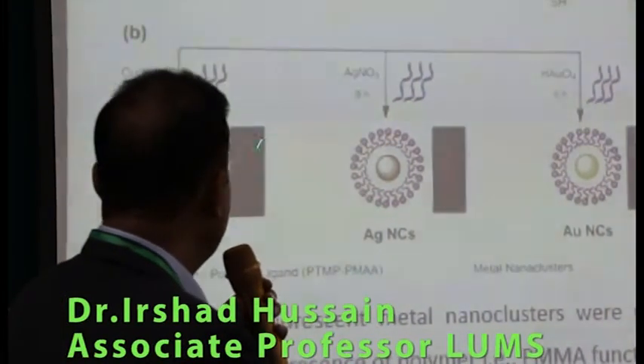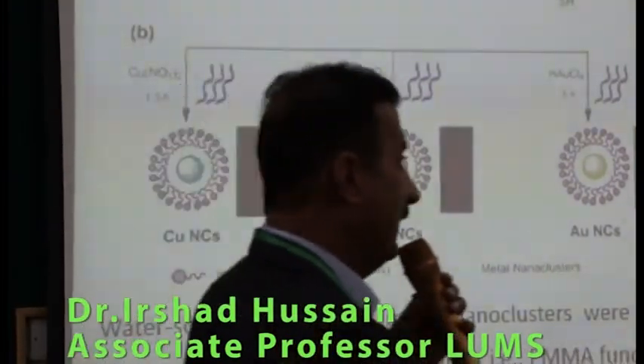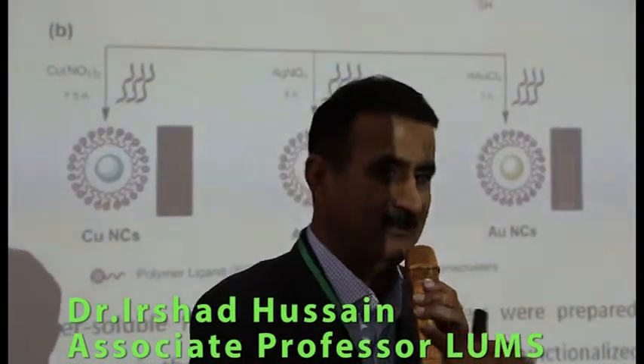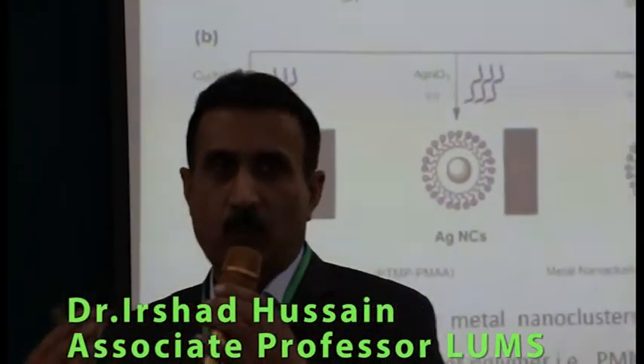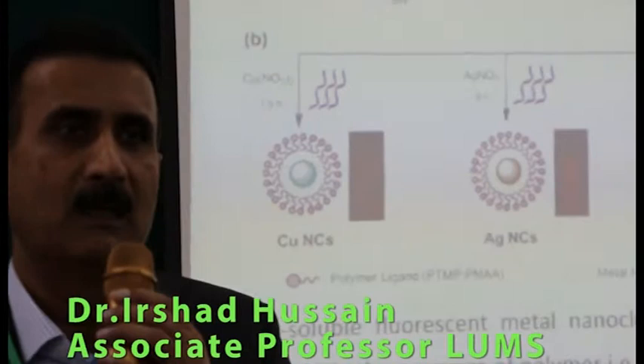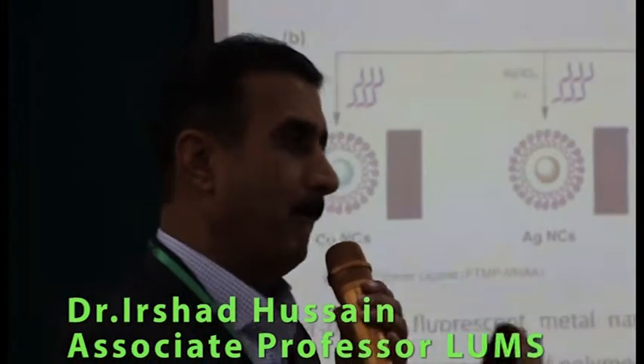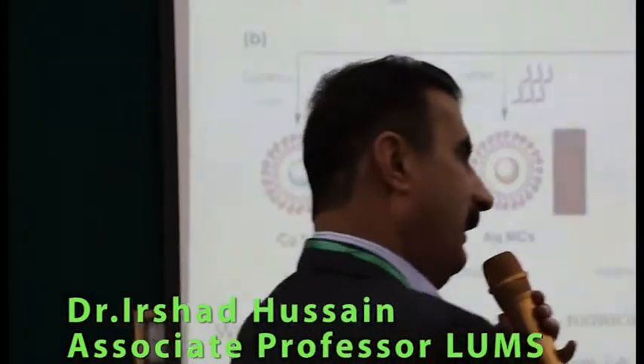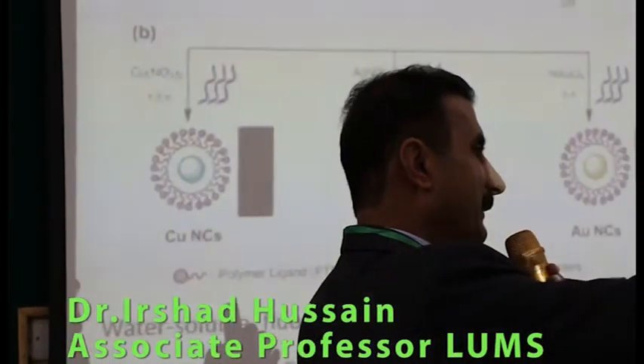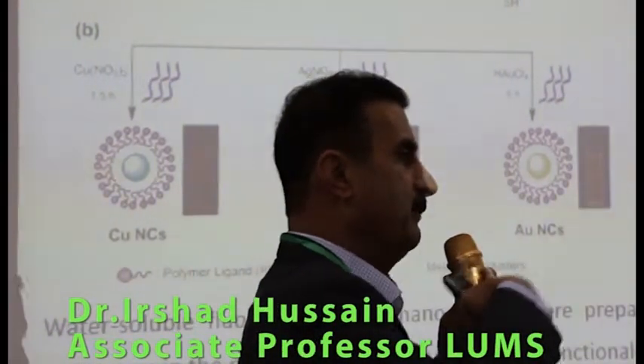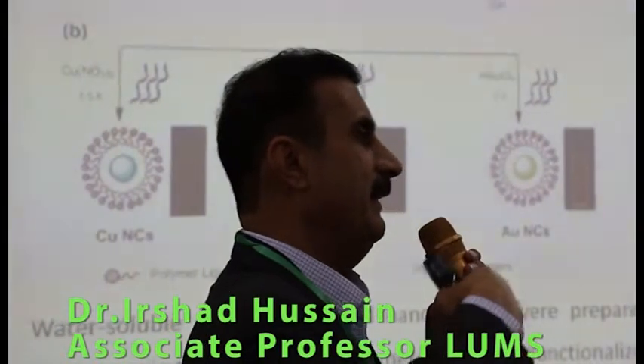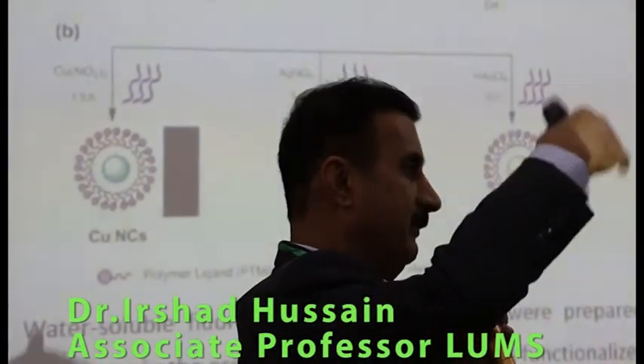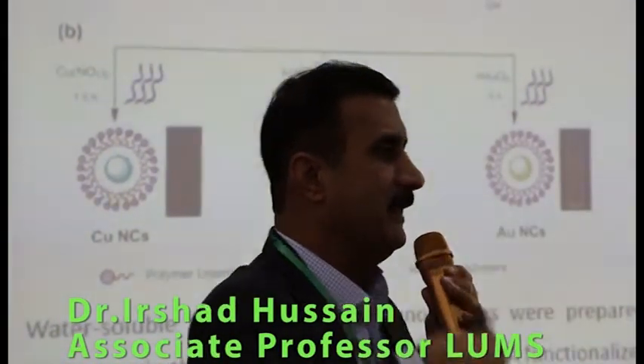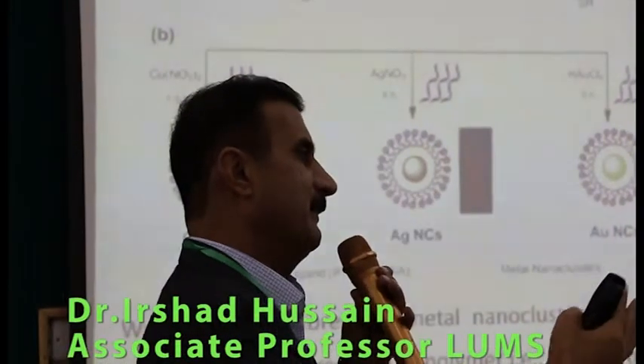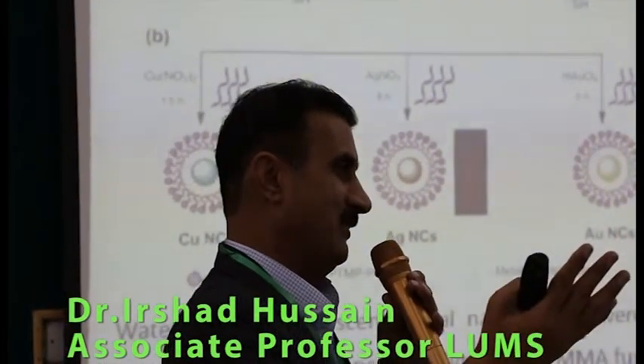metals. And you will see they are fluorescent. So they are not metals in this size regime. Normally, we know gold, silver, palladium, platinum, all these are metals. But they are metals only when the particle size is bigger than 2 nanometers. When you make the size less than 2 nanometers, then their valence band and the conduction band get separated from each other and they start behaving like semiconductors and even like molecules.